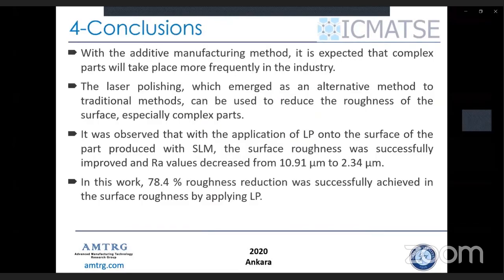As a conclusion, with the additive manufacturing method, it is expected that complex parts will take place more frequently in the industry. The laser polishing, which emerged as an alternative method to traditional methods, can be used to reduce the roughness of the surface, especially complex parts. It was observed that with the application of laser polishing onto the surface of the part produced with SLM, the surface roughness was successfully improved and RA values decreased from 10.91 micrometers to 2.34 micrometers. In this work, 78.4% roughness reduction was successfully achieved in the surface roughness by applying laser polishing.